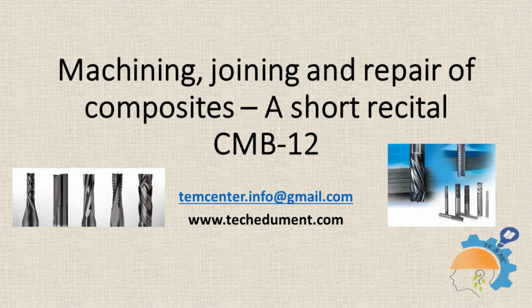Composite materials are more difficult to machine than metals mainly because they are anisotropic, non-homogeneous, and their reinforcing fibers are very abrasive. During machining, defects are introduced into the workpiece, and tools wear rapidly. Traditional machining techniques such as drilling or sawing can be used with proper tool design and operating conditions. Non-traditional machining methods such as waterjet, laser, and ultrasonic machining are also used. All these are very briefly discussed in this video.